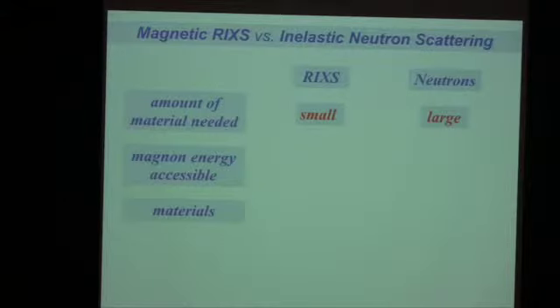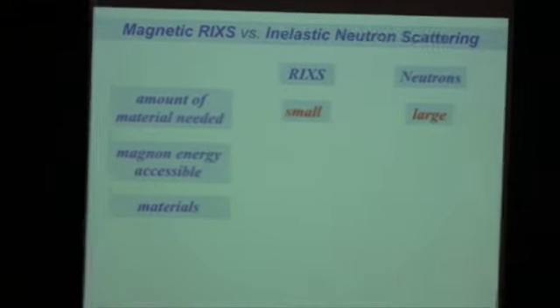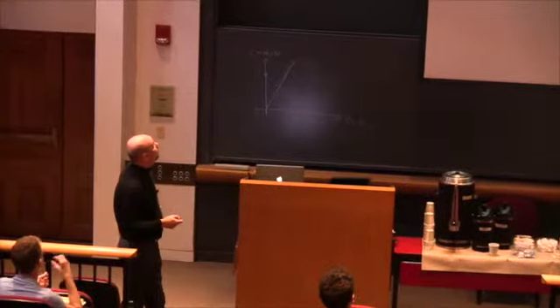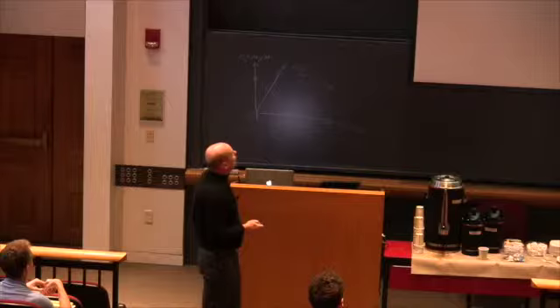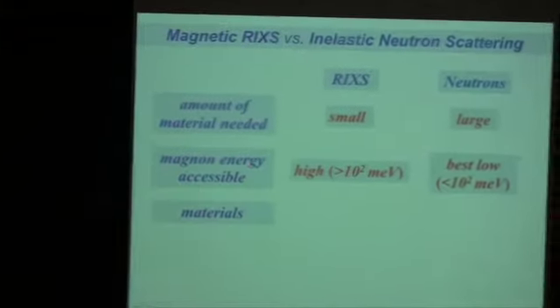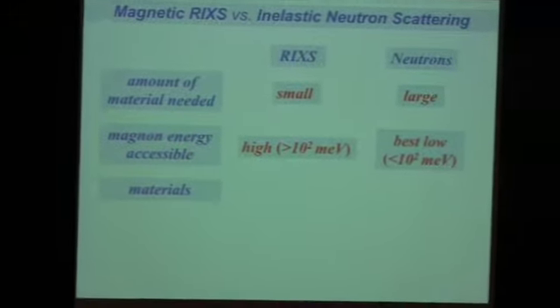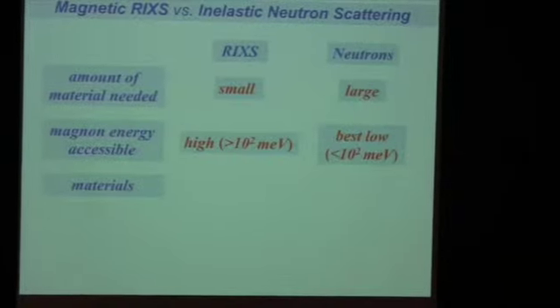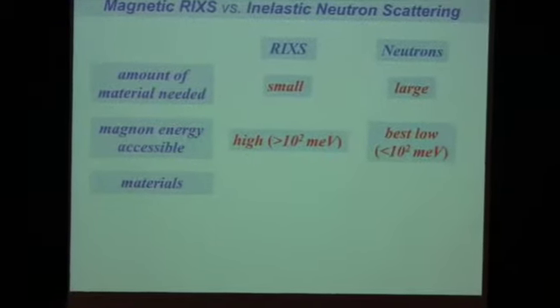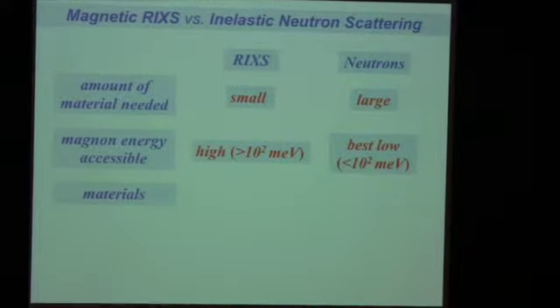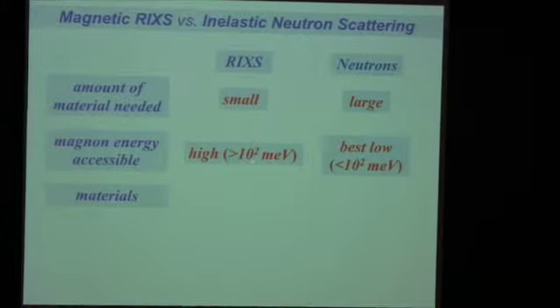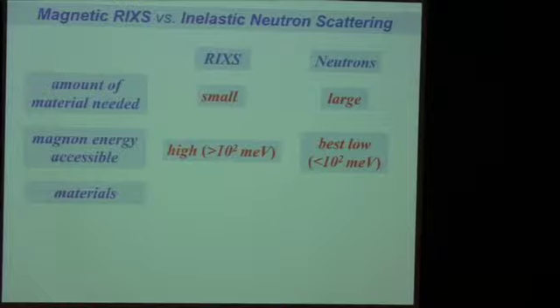So for people interested in oxide heterostructures, for instance, RIXS is a perfect tool. Inelastic neutron scattering is a tool that doesn't make much sense for that. So that's a good thing for RIXS. The bad thing is which magnon energy is accessible. Well, high energy is not a problem. Low energy magnons, well, you have to take care of your resolution, which is hopefully 10 millielectron volts in a year or so, if Brookhaven holds its promise. But still, very low magnon energies will never be accessible by RIXS. Neutrons can measure parts of millielectron volts, micro electron volts. This will never be accessible by RIXS. Neutrons are best, as I said, at low energy.